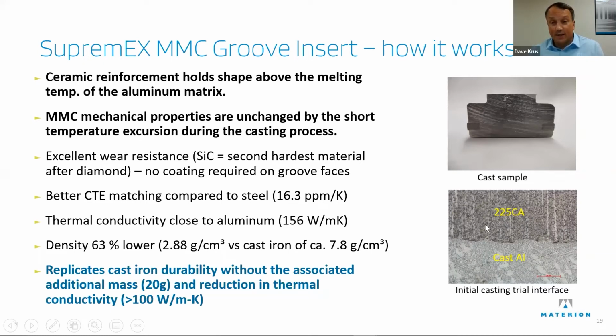Now, you can see this is the first casting trial. You can see a little porosity at the interface, but if you do what they do with the cast iron rings and dunk it into molten aluminum first, and then put it into the die casting mold, which shoots in very quickly, you've got a very good bond there. So you've got that great wear resistance. The CTE match is better too.